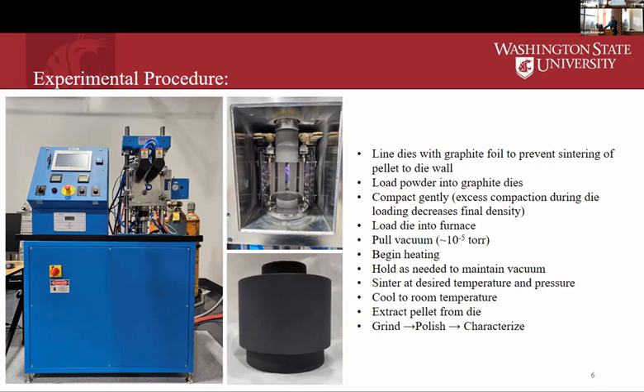Then you cool to room temperature. You'll see in the next slide that we tried to use a relatively high cooling rate to almost quench the grains and stop grain growth as much as we could, because we were targeting smaller grains. After that, you can extract your pellet from the die, and then grind, polish, and characterize it.